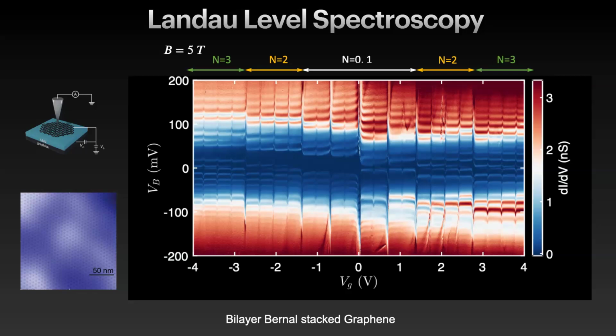So this is kind of like good hygiene. I hate to say it like this, but you should have good STM hygiene. The way we prepare our tips is that we know where our tip has been. We clean it on a piece of copper, and it turned out that this practice serendipitously gave us a work function matched tip to that of graphene samples. Carbon and carbon, these tips have very close work functions. We can actually see work function differences between the tip and the sample, and we can use the Landau levels to measure it.